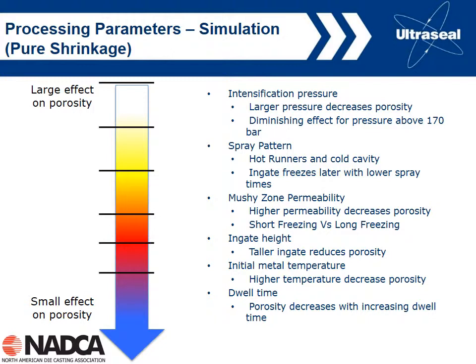Above this, we get a diminishing effect. If we go above 2,500 psi to maybe 5,000 psi, the porosity is only slightly reduced. Maybe we go from 1% to 0.75% or so. So we get this diminishing effect with pressure, and we'll talk about this later as we go through today's webinar.